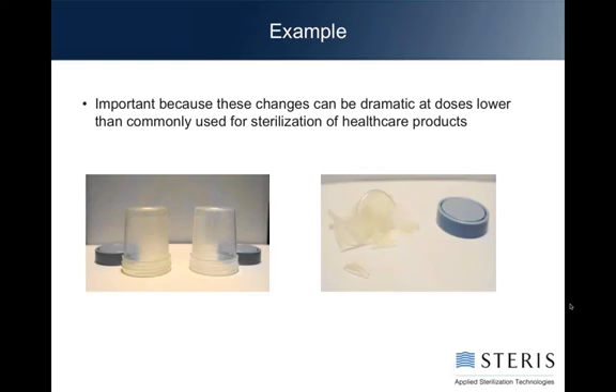As an example, it's important to know that all these changes can be dramatic at doses much lower than you're probably thinking you're going to need for a sterilization process. For example, the first thing most people think about when they're talking about a radiation stable product, they're thinking, oh, I can run this 25 to 40 or 50 kilogray. In the case of a natural polypropylene, the simplest polypropylene you can find, if you work with that material, it will never be able to tolerate the types of doses you need to get a 10 to the minus 6 sterility assurance level. These pictures here are just a quick, easy example.